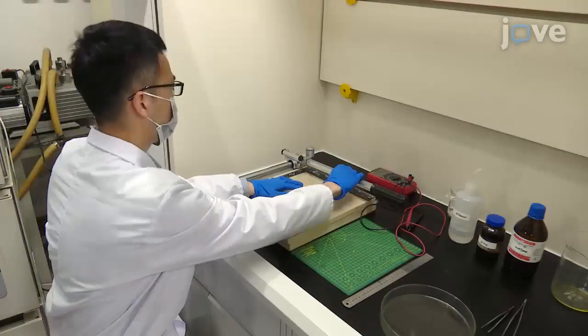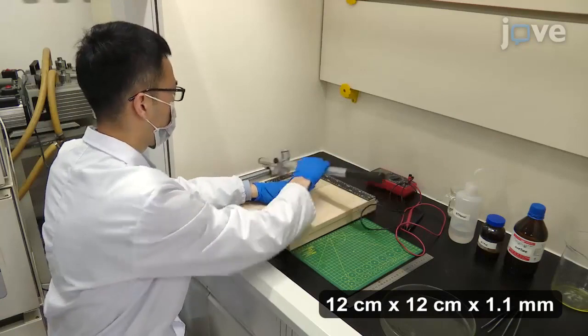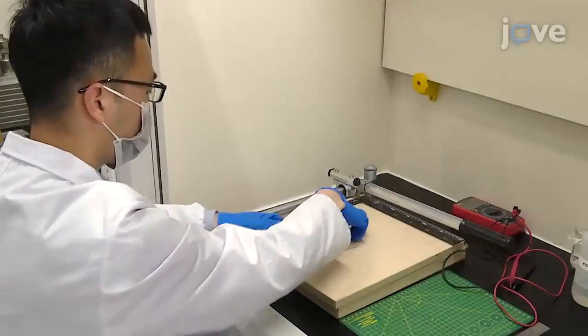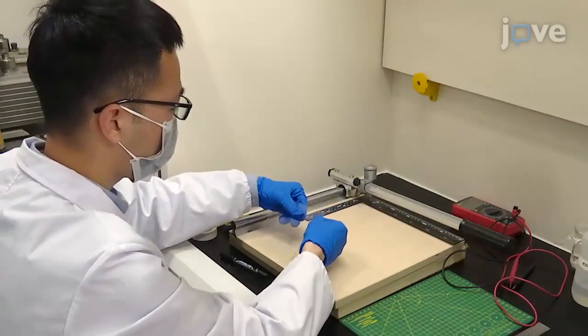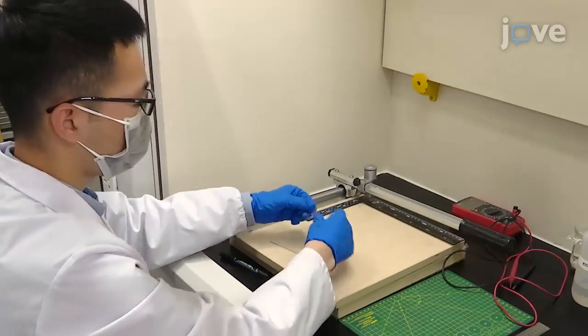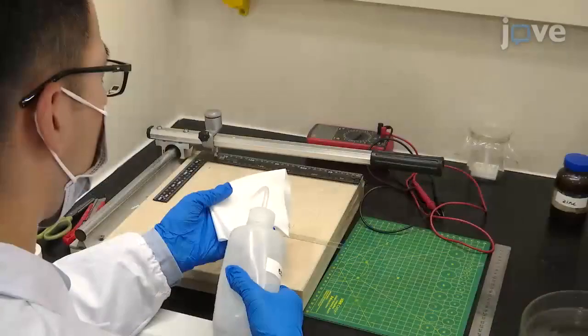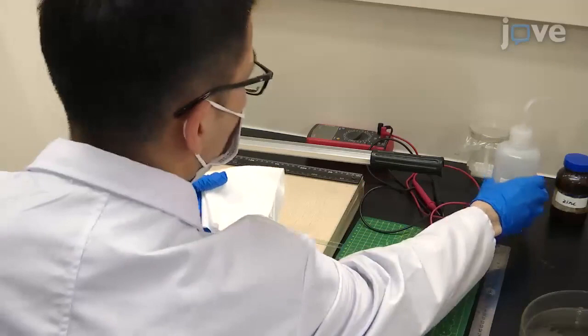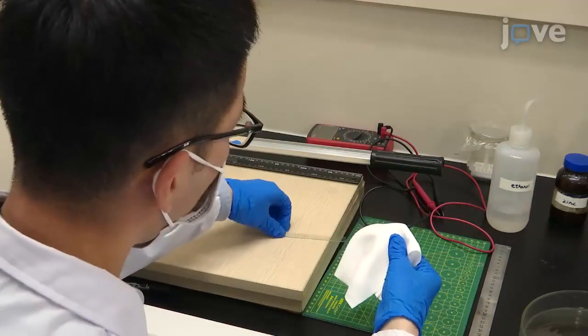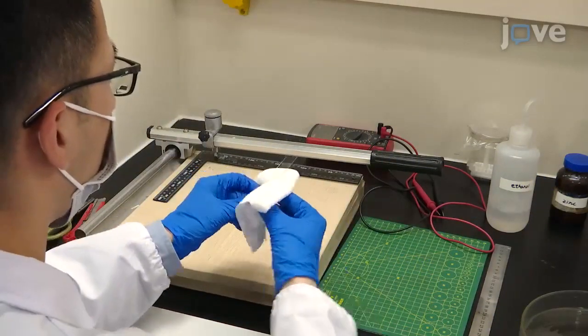To begin the procedure, cut a 12 cm by 12 cm piece of ITO-coated glass with a resistivity of about 10 ohms per square into 15 mm wide strips. Clean the ITO glass strips with a dust-free cloth and pure ethanol. Allow the ITO glass to air dry.